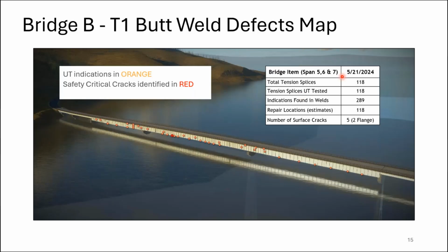So you can see by the numbers in this table, we had a total of 118 splices that we considered to be in tension that were welded, and we tested all of those on bridge B. And in those welds, we found 289 individual indications and 5 surface breaking cracks. So the surface breaking cracks, a collaboration between FHWA, CDOT, and the designers decided that to reopen the bridge to traffic, we needed to address all the surface breaking cracks before it could be reopened.